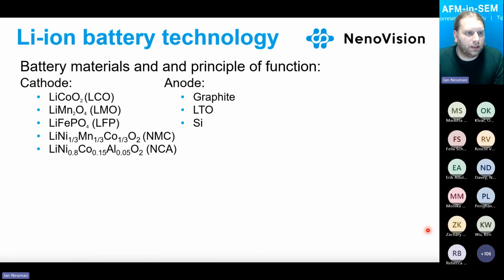In the case of the cathodes and anodes, there are several types of materials. The most important types are lithium iron phosphate and currently lithium nickel manganese cobalt oxide. But generally, we have about 5 families of cathode materials and 3 families of anodes. The main anode material is graphite, then LTO and silicon, but silicon is used mainly as an additive.